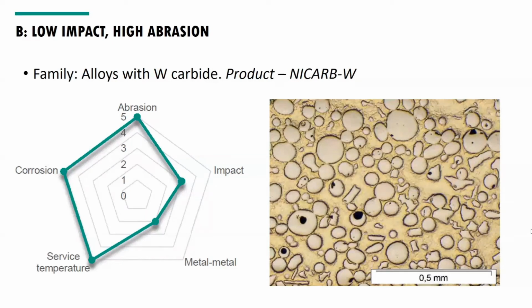So here we have a product called Nicarb, and you can see the microstructure is very different. It's a nickel matrix because we use a nickel sheath or strip. The reason why we do that is because of the toughness that we get from the nickel, but also we can weld at a much lower temperature, which means that the tungsten carbide particles do not dissolve in solution and they maintain their size, which then gives it the abrasion resistance. If you do not use a nickel strip, then a lot of those tungsten carbides, which are quite expensive, will dissolve into the solution, and you'll end up with a tool steel type of material instead. So that's what we use for really, really high abrasion type of applications where nothing else works. Next slide.